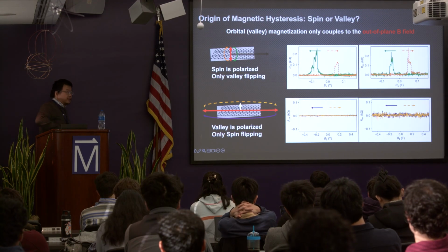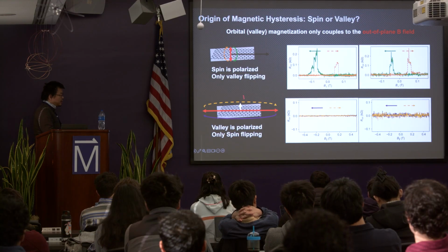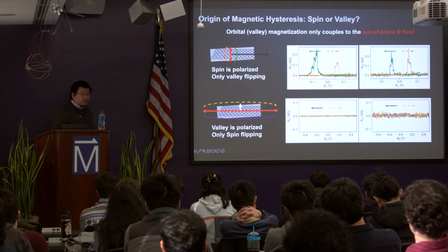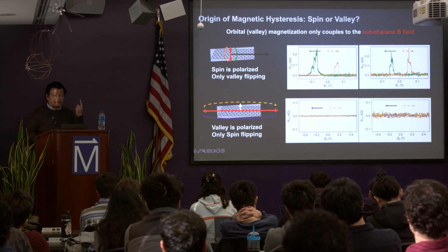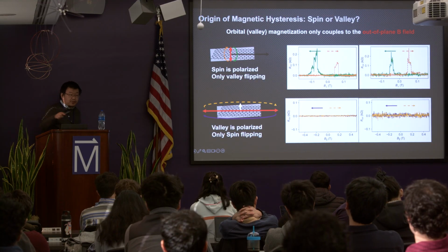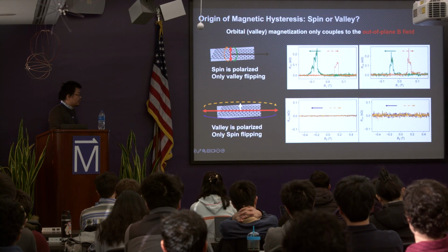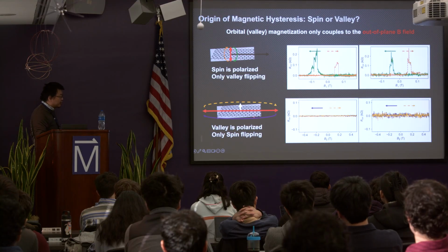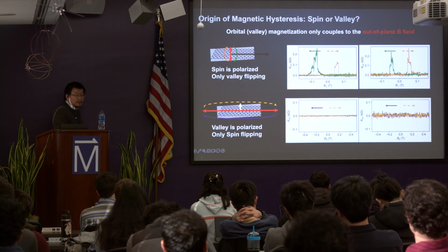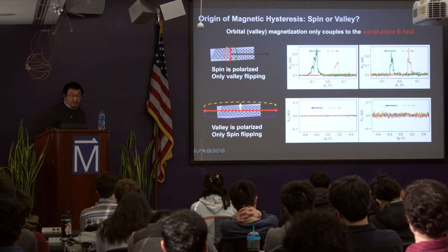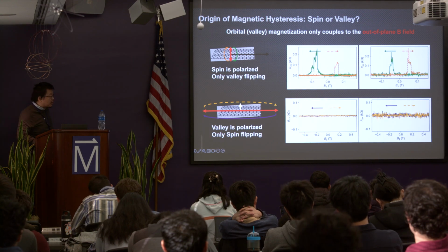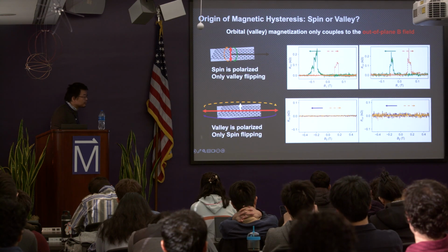And then you can do it the other way around. You can first add the out-of-plane magnetic field, and then your spin is fixed, your orbital is fixed. If it comes from the spin, if you sweep the in-plane magnetic field, you should see hysteresis. But if you sweep the in-plane magnetic field in this case, you do not really see hysteresis. So basically this is evidence that this hysteresis is coming from the orbital instead of the spin.